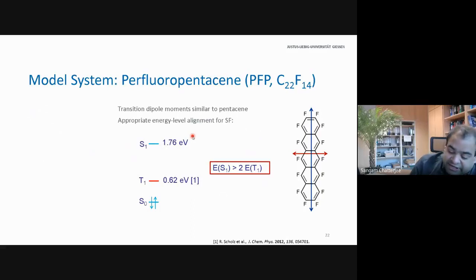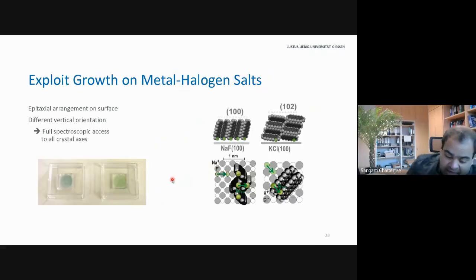We did the sanity check for singlet exciton fission. We came to the result that it actually works by the energetics, because the singlet energy is more than double the expected triplet energy. And the nice thing is our favorite grower at that time could synthesize very well-ordered crystals exploiting pseudo-epitaxy, or exploiting the organization on metal halogen salts, the crystal structure.